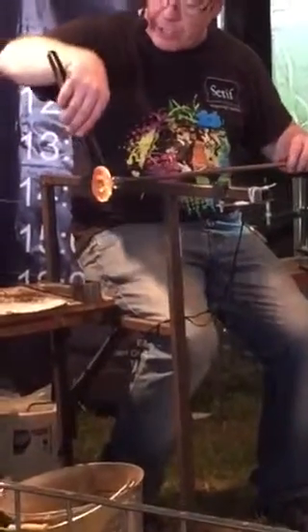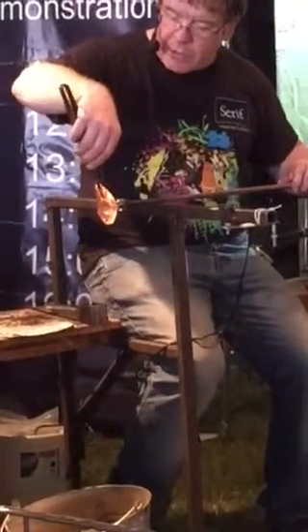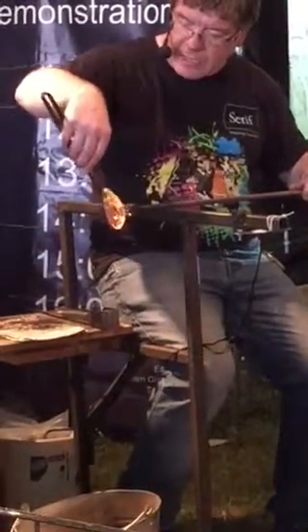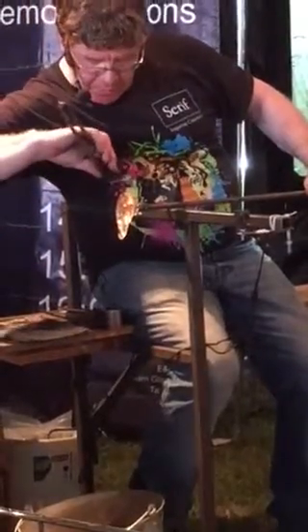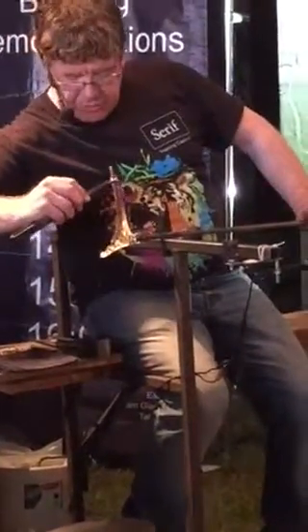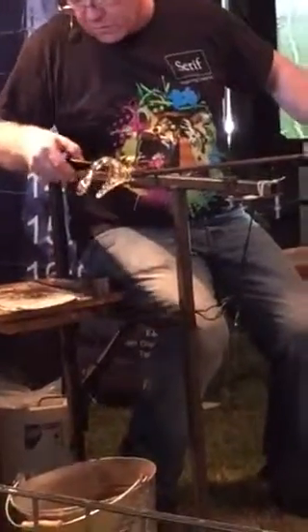So what I'm doing right now is just watching the colour of the glass. When it's the right shade of orange, I know it's time to start doing these little tiny tweaks. Now, each of these little movements, I've got to do at just the right time and in the right order. If anything goes wrong with this, I basically have to throw this away. There's no second chances. So, just watching the colour of the glass, working my way around. Just give that a few seconds to cool down.